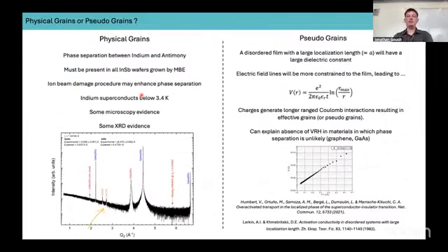So one big question would be, what is the origin of these grains? To us, there's two main mechanisms: physical grains, something like a phase separation between the indium and the antimony. This would have to be present in all MBE grown indium antimonide wafers grown on gallium arsenide. And it's very likely that this ion beam damage procedure may enhance this phase separation. If you imagine a situation where you're knocking off antimony atoms, which then manage to group together, forming this indium-rich phase. This supports other observations we make, like this overactivation, which has been linked to superconductivity. And there's also some X-ray diffraction evidence. This is an X-ray diffraction plot, and each peak corresponds to a material trace.